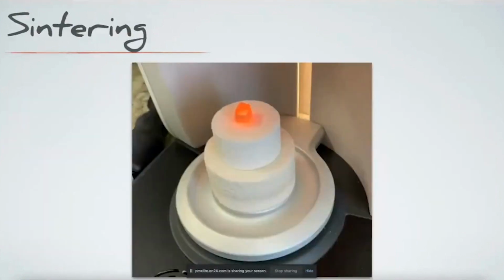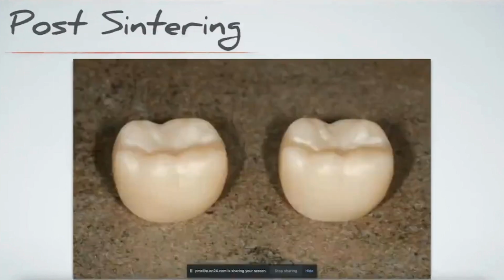Once it comes out, it's very hot. You see it kind of smoking orange here, right? It'll have a warning on the screen, do not touch, because it is hot. 1100 plus degrees when that's dropping down. So we're going to let it cool. And as it cools, we end up with this kind of nice restoration. Now, what I'm going to show you here, and this is a